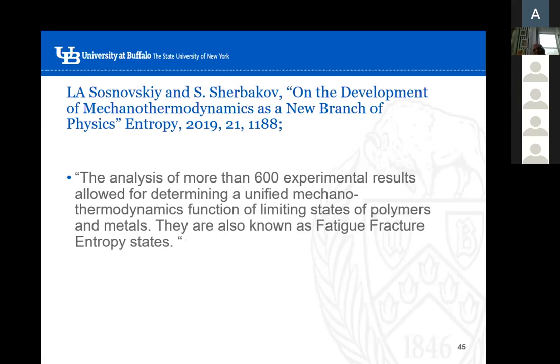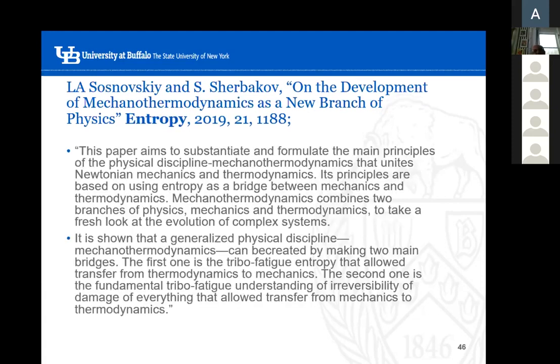Essentially, they tested 600 samples by changing parameters, again, load level, average load, mean stress level, geometry, loading, frequency, like for example, also tension compression versus tension. Tension will give you different SN curves if you test the same sample in tension versus tension compression. So that's why they ended up with 600 sets of data. Again, they end up with the same conclusion.